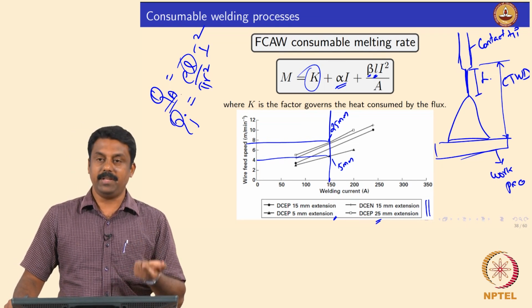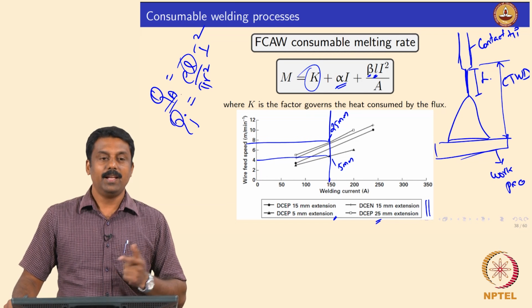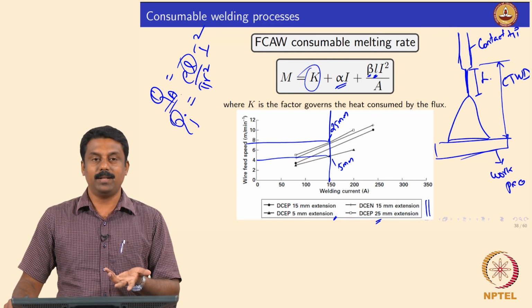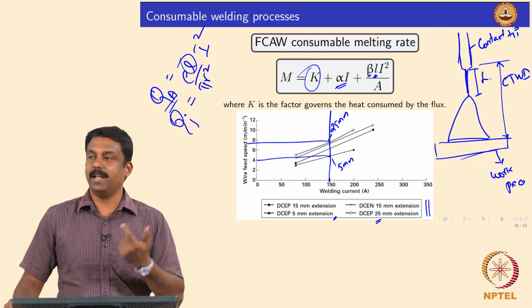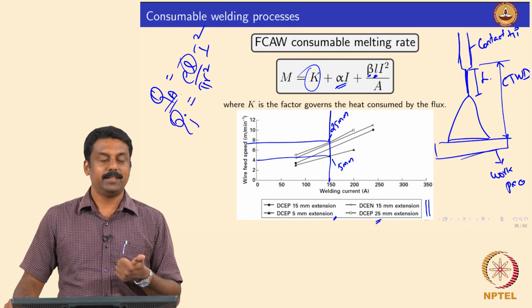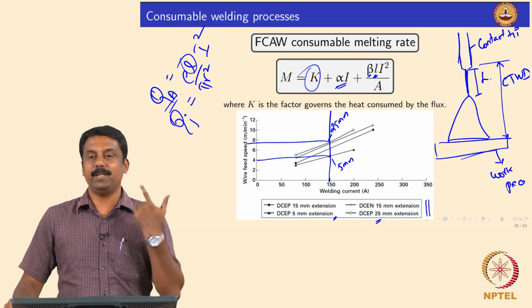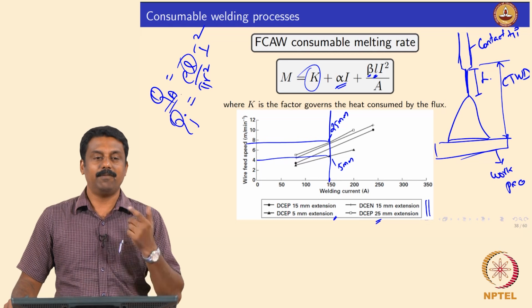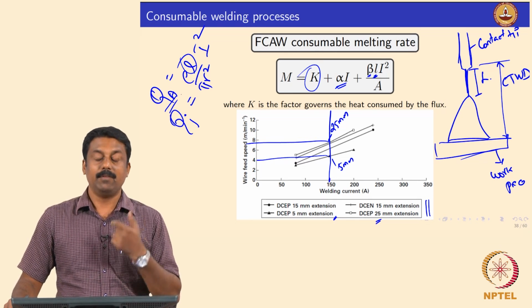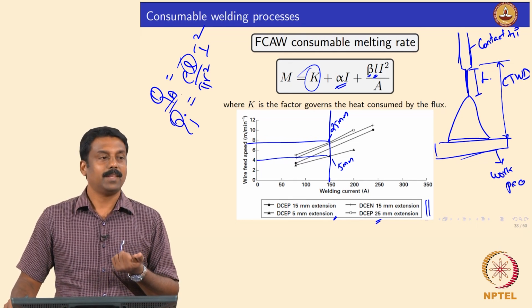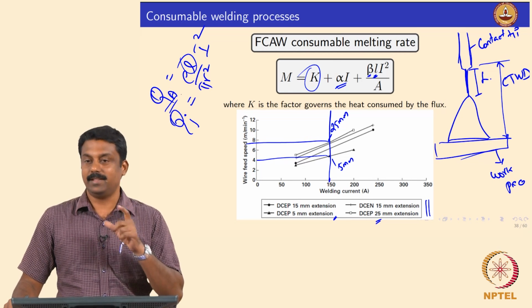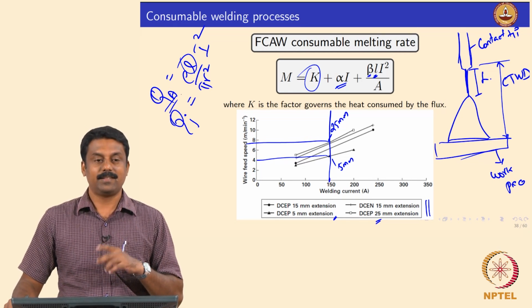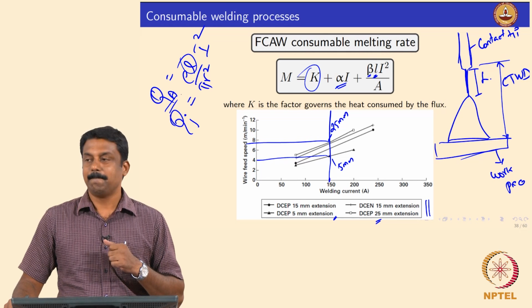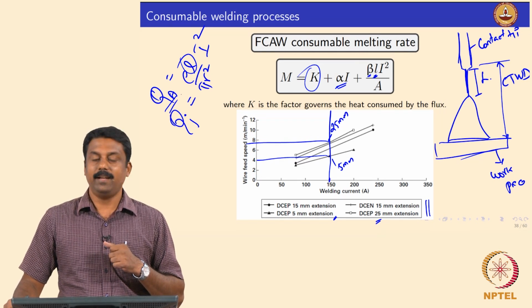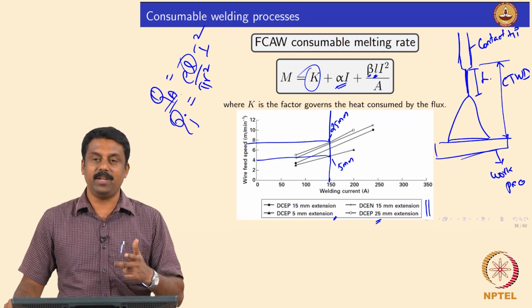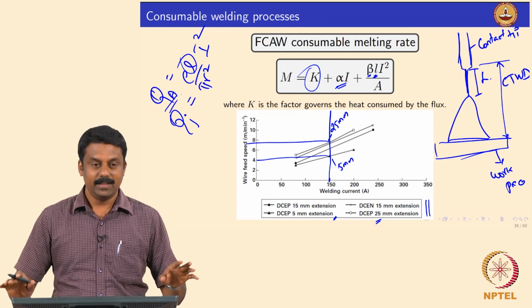So, the current can be changed. In the resistance heating part and Joule heating part, there are two other parameters, the diameter and the length. So, you fix a diameter for a given weld diameter, consumable diameter. So, what other factors can be changed? The length, right. The length is stick out length L, right. So, two parameters independently can change by fixing everything.